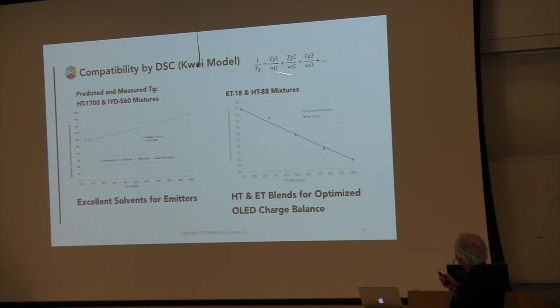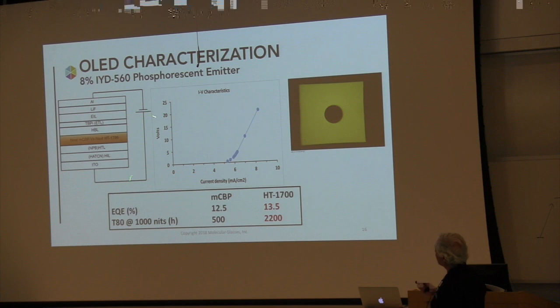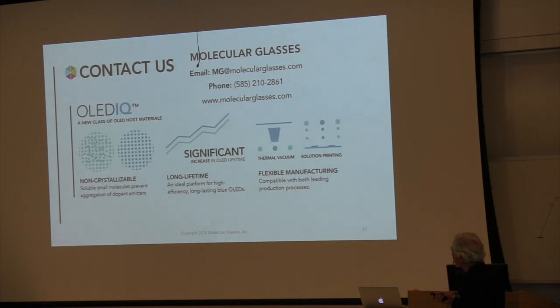And the other thing is we can mix our things. So if we want electron and hole transport, we can mix and match to get whatever characteristics we want. And our materials work. They light up. And one of the things we found was that in this comparison, the lifetime of the OLED with our material was much longer than in the standard material. Sort of confirming our hypothesis that we would improve the lifetime of the OLED.